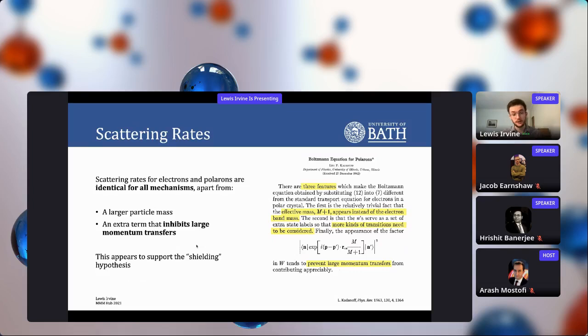And I'll show you the scattering rates in the next slide. But the broad idea is that the scattering rates are very similar for all mechanisms, apart from a larger mass and an extra term on all of the scattering mechanisms, the effect of which is to inhibit large momentum transfers. So basically, when you have a scattering mechanism, it can scatter by an angle, and it inhibits large scattering angles. This was noticed by Kadanoff. These highlighted bits here are basically saying the same thing, as well as these extra transitions, which he later ignores as well. But this appears to support the shielding hypothesis, right? That Zhu and Podzorov were on about.